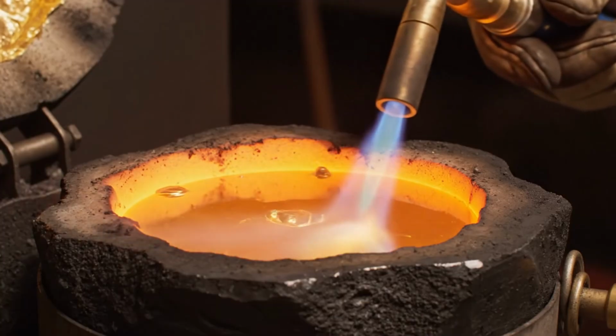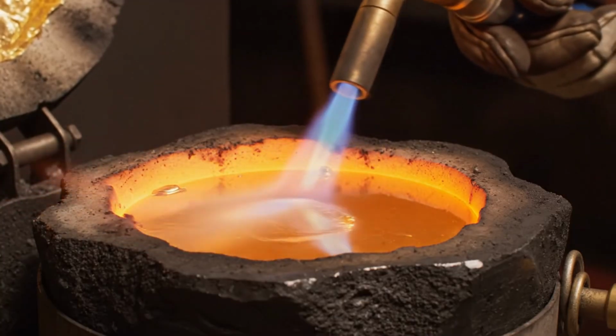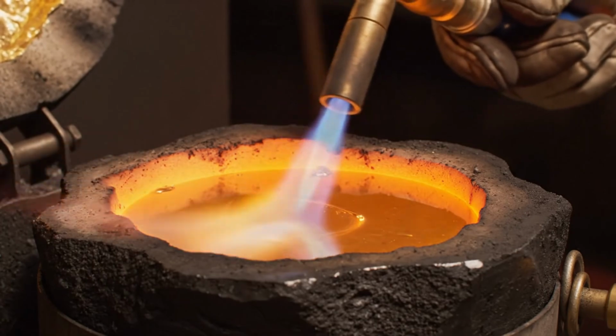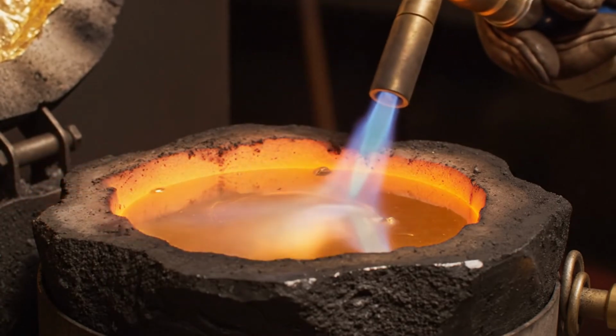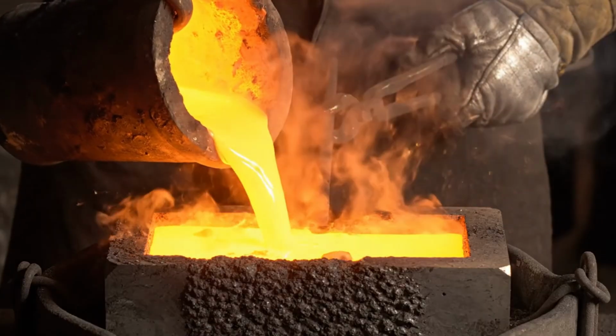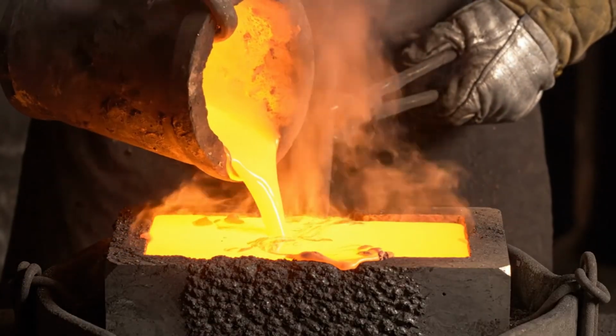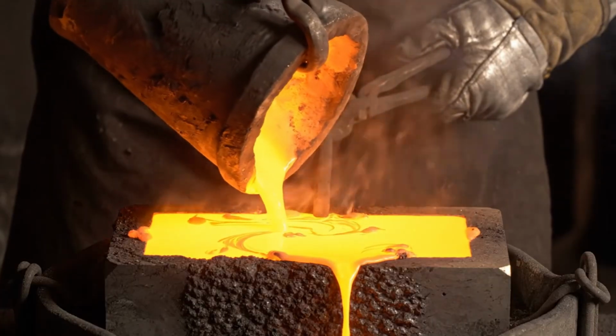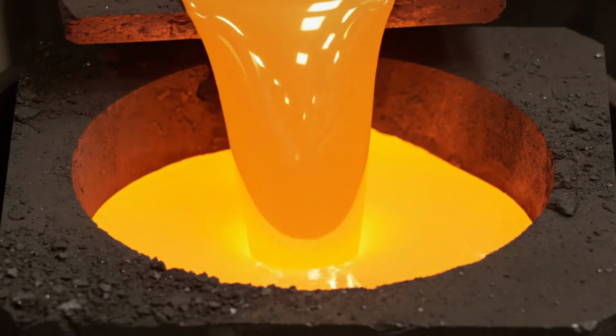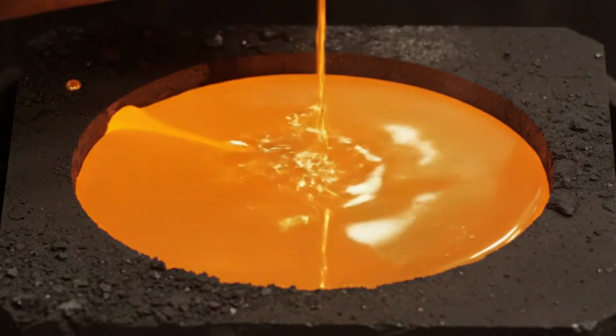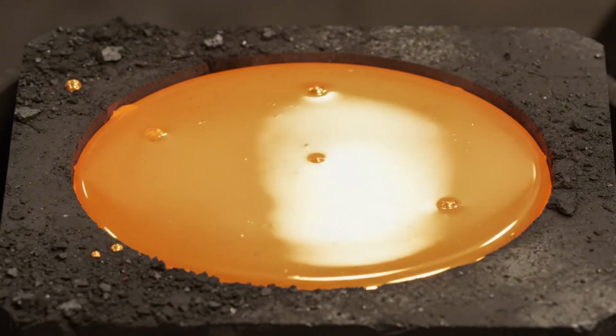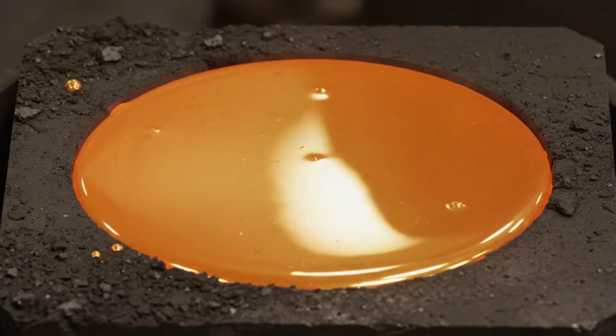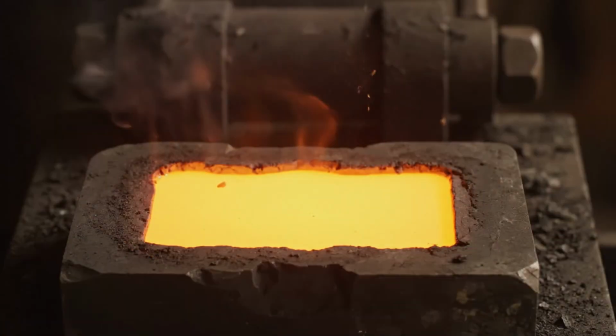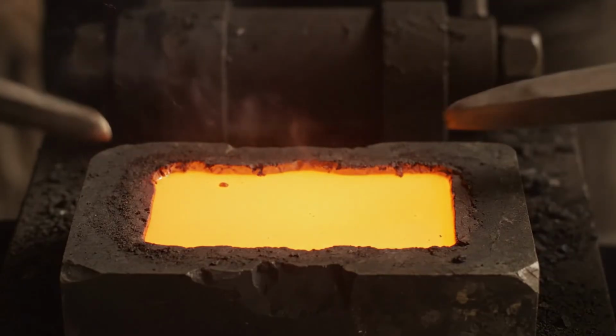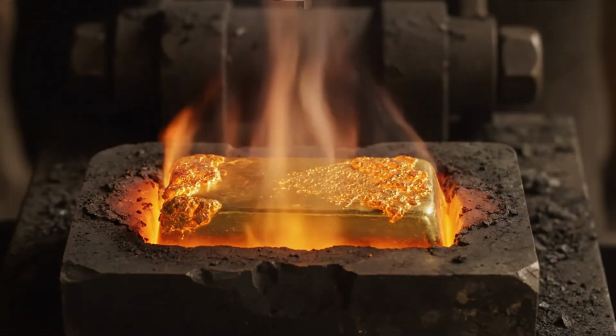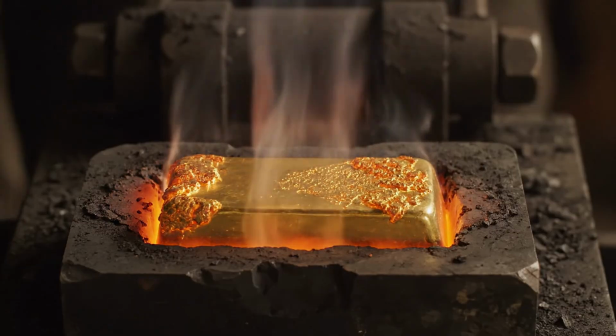A craftsman creates a controlled flame barrier over the liquid surface, preventing oxygen from interacting with the gold and causing any unwanted oxidation. The glowing orange liquid is poured by hand into graphite molds, a moment requiring steady nerves and years of practical experience to master. As the metal hits the mold, it settles instantly, the liquid surface tension smoothing out into a perfect mirror before solidifying almost completely. A burst of flame dances across the cooling bar, a visual signature of the intense thermal exchange happening as the gold finally hardens.